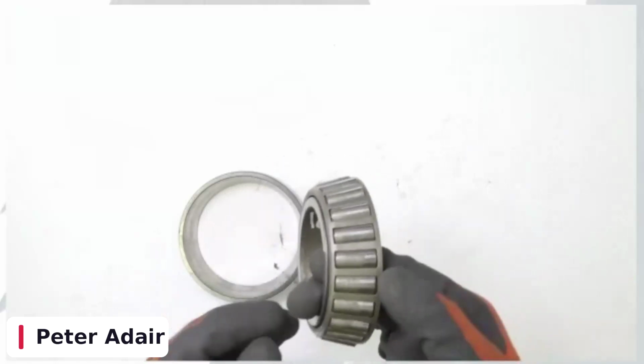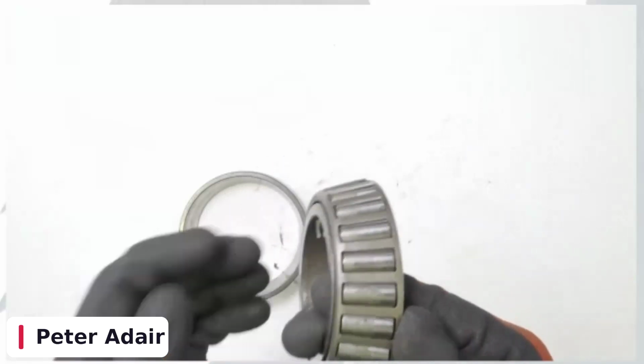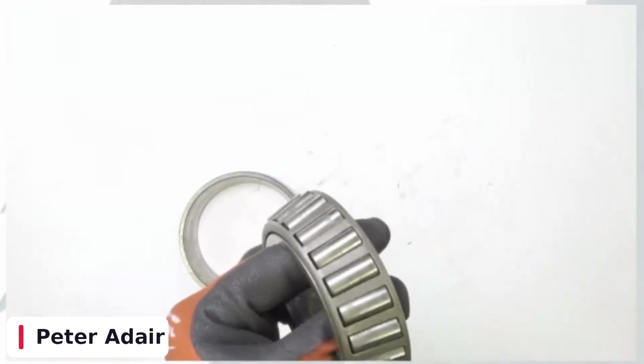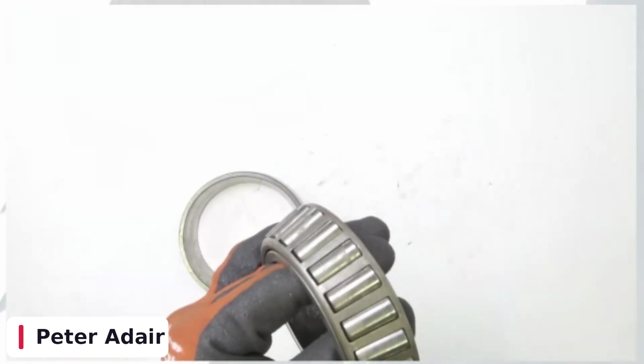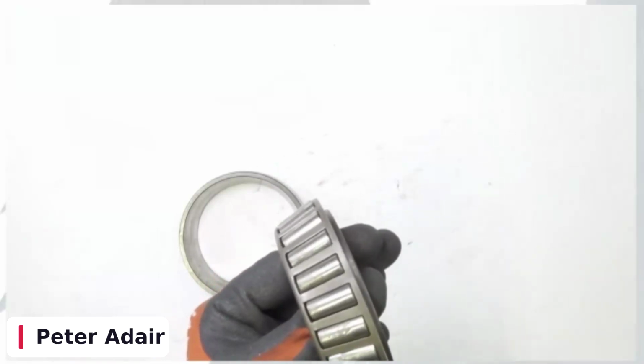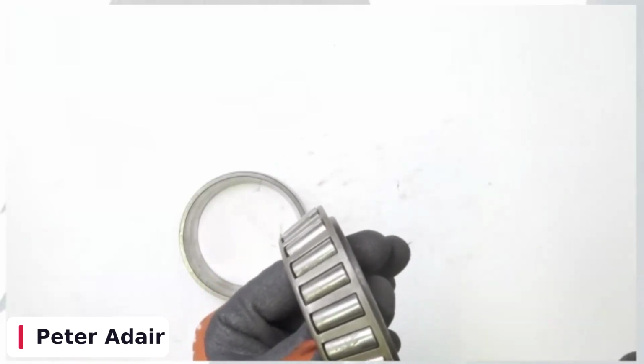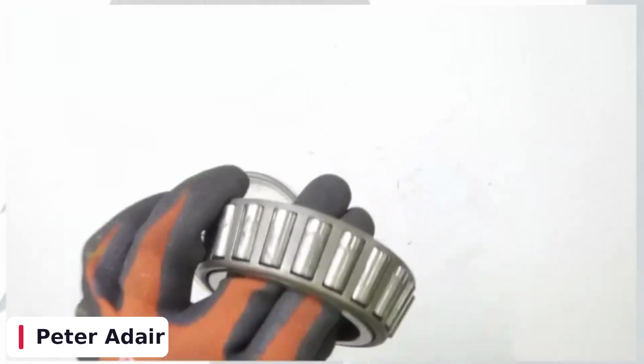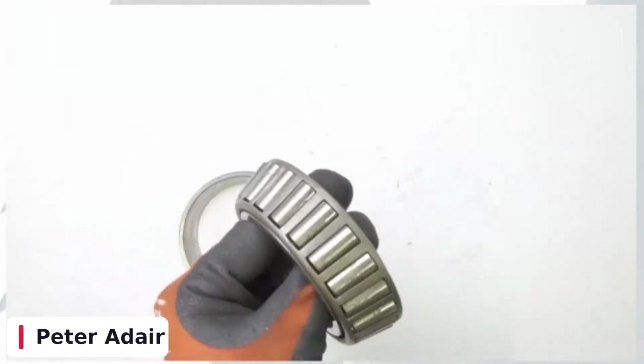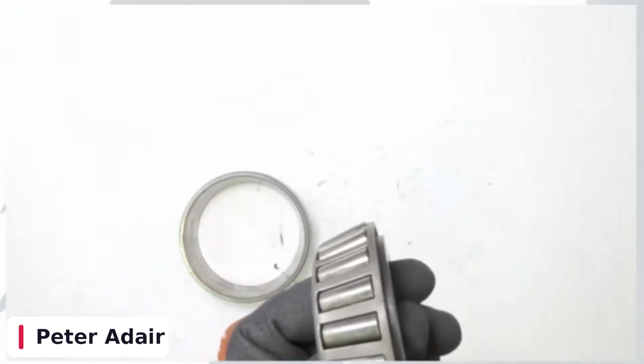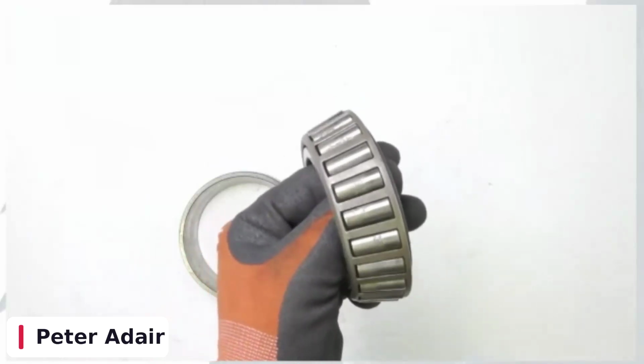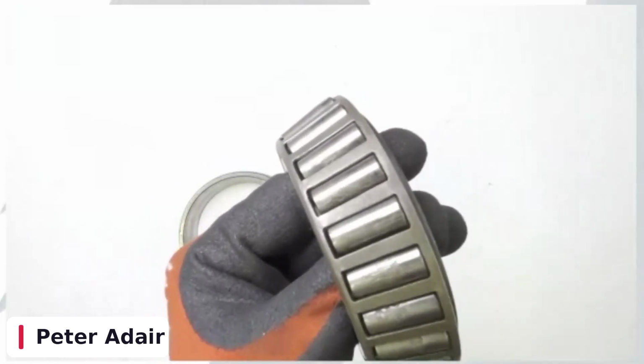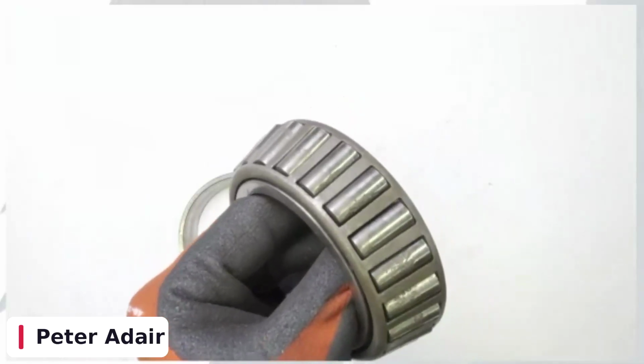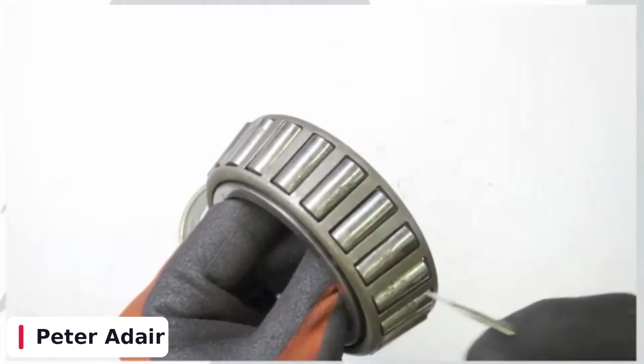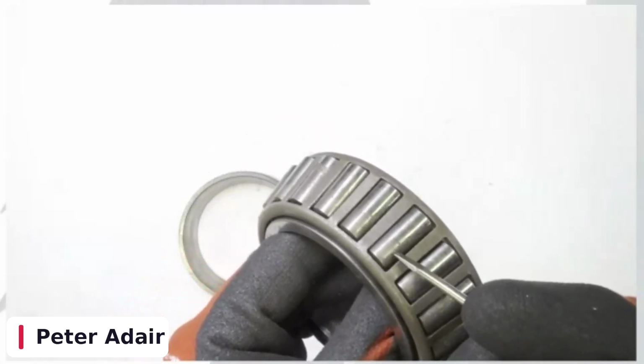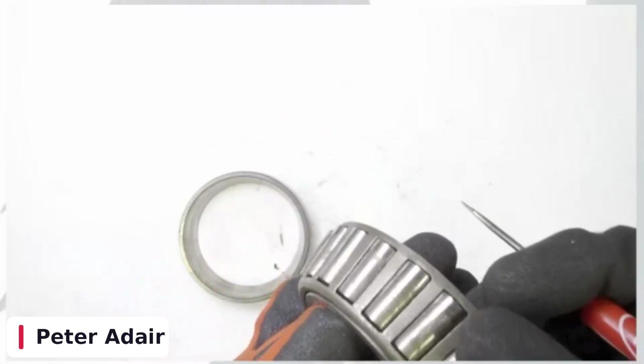Well, in order to get spalling that we're seeing here on camera, you have to get rid of the oil. Now, does that mean it didn't have any? No. What did we say is a good sign of no oil? Burnt. This is not burnt. This looks pretty good. It's got a little rust on the cage, but it's been sitting in the training room for a while now. But if I look at these rollers, they're kind of spalled at the small end of the bearing. Now, what is spalling?